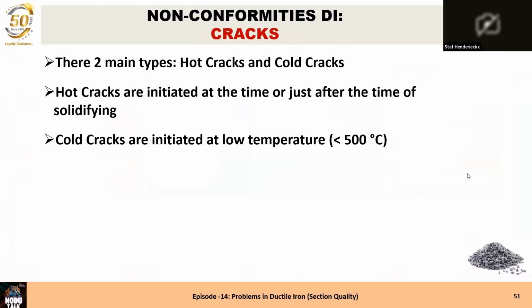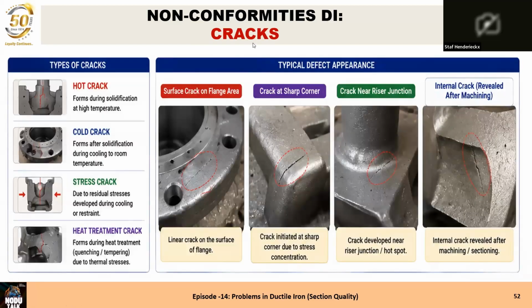The cold cracks are initiating at low temperature. It's mostly lower than 500 degrees C, and it's mainly with heat treatment that it will happen, or sometimes during the cooling down in the mold, when we have a very thick section compared with a thin section, there it can also happen. Hot cracks, cold cracks, stress cracks, that means that's mostly a cold crack also, and a heat treatment crack is also a cold crack. It can be linear on a surface.